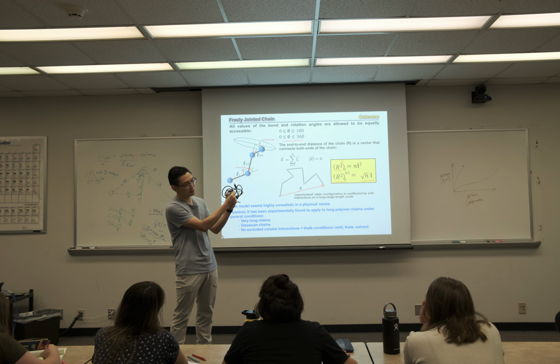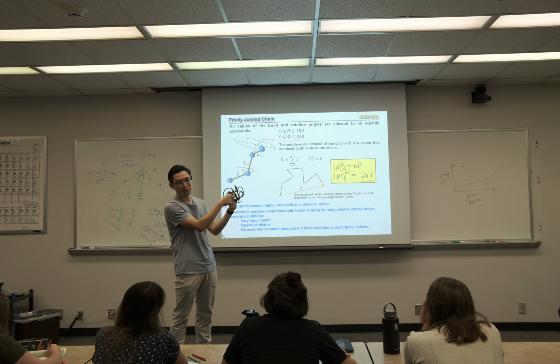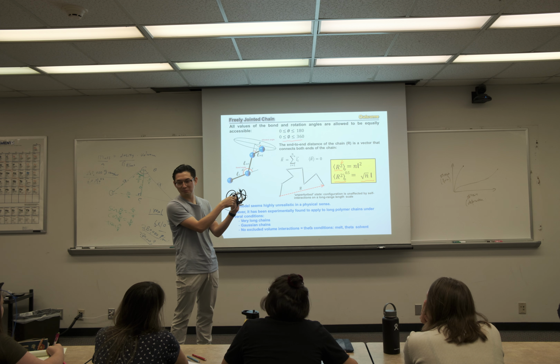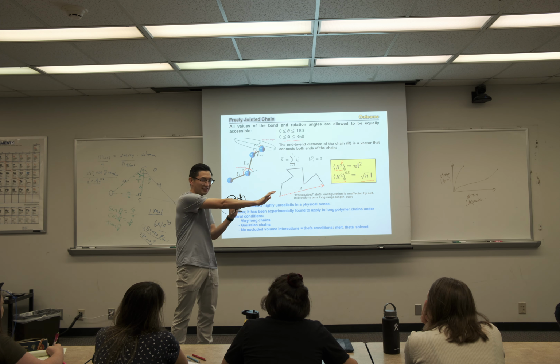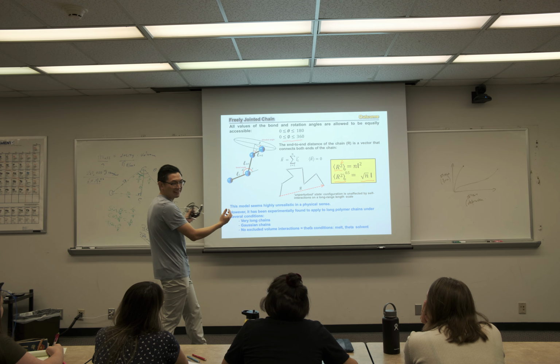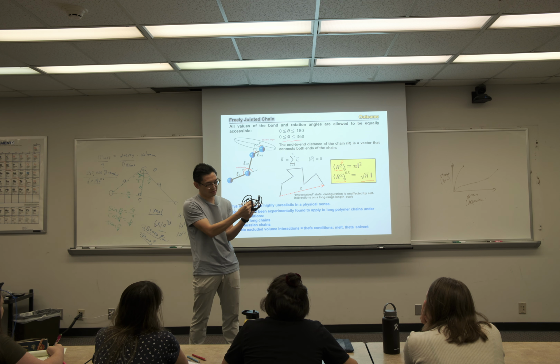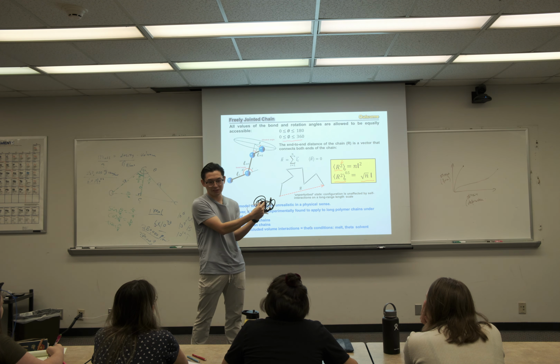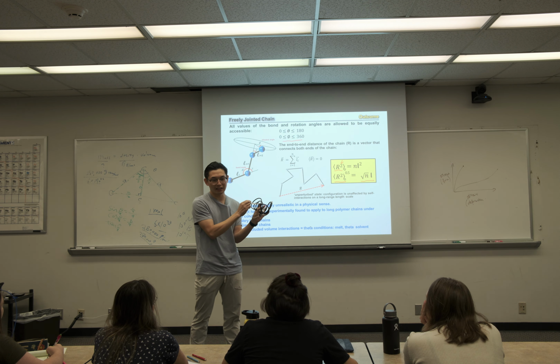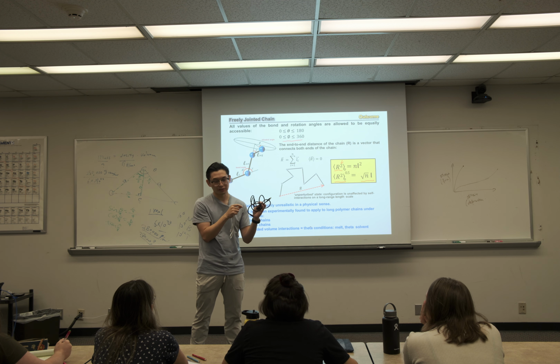It's closer to itself, but it's also closer to a neighboring chain. So they both say, get out of my room, I want more space. It says, go that way. The other guy says, no, go that way. So this chain feels pushing force from both sides, and they happen to cancel each other out. So there's no net expansion. If we didn't have the neighbor, it would only have expansion from itself, okay?